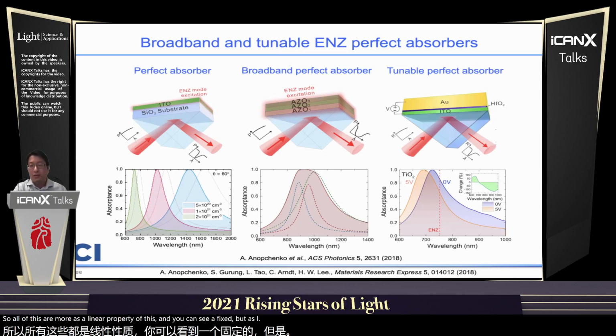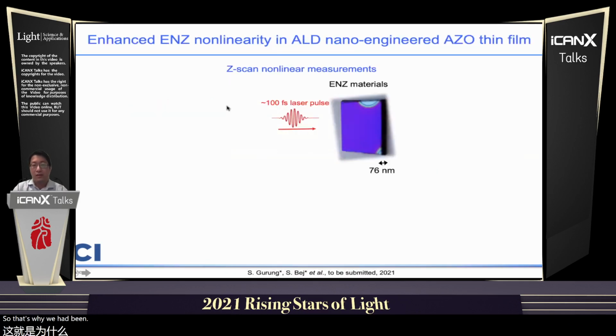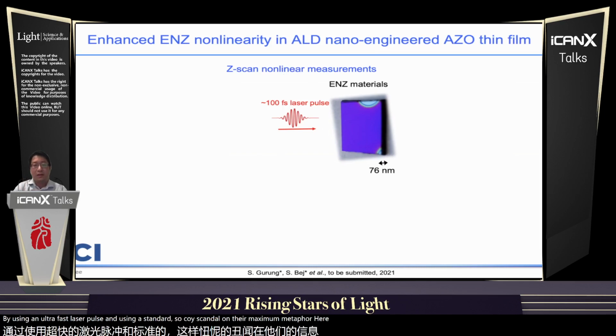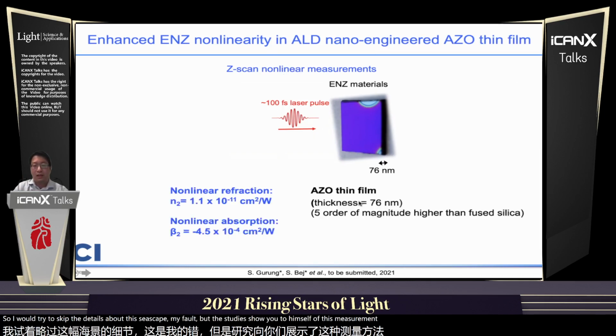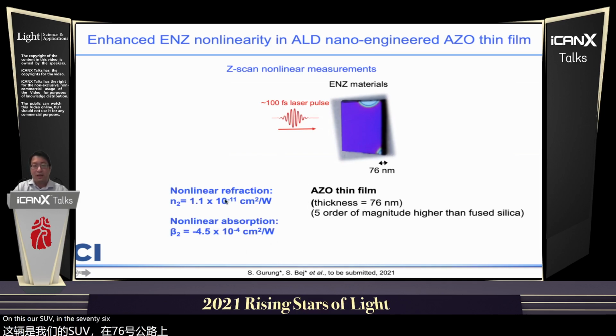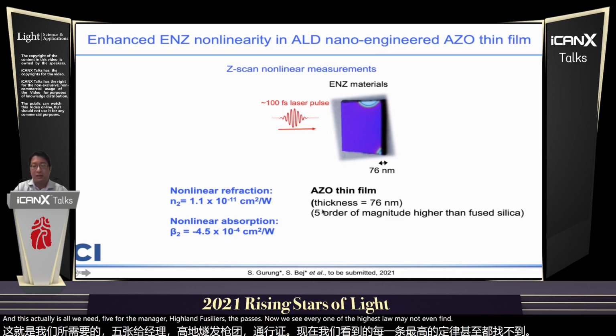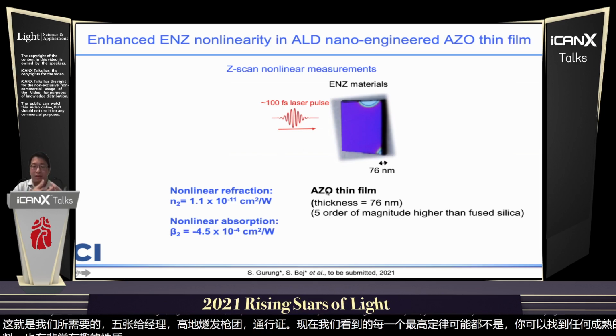But as I mentioned to you, one of the quite exciting properties actually is the nonlinearity of the material. So that's why we have also been looking at the nonlinear effect of this material by using an ultrafast laser pulse and using a standard so-called Z-scan nonlinear measurement method here. I will skip the details about this Z-scan method, but just show you the result of this measurement on this AZO thin film with 76 nanometer thickness. And this is the nonlinear refraction and absorption coefficients, n2 and beta 2, you can get. And this actually is already 5 orders of magnitude higher than fused silica glass. And I would say it's one of the highest nonlinearities you can find in any material. So that's why this kind of ENZ material has really interesting properties, actually the high nonlinearity here.